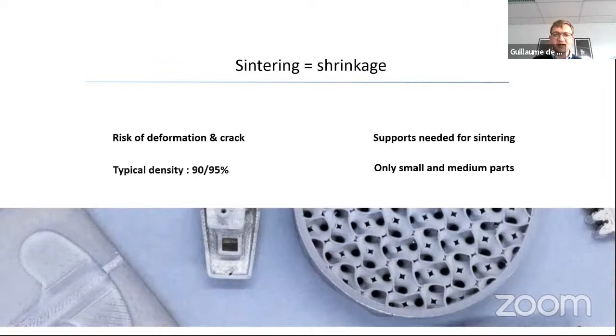The one thing which goes with that is if you have some densification without melting, the material needs to come from somewhere, and what happens is the part will shrink. And that's really one of the major problems with MIM-like technologies. If you sinter a part, you have shrinkage, and shrinkage is going to pose a few problems. The first one is obviously you'll have some risk of deformation and cracks. Secondly, you will get to dense metals, but not fully dense. It's very difficult by a sintering method to get to more than 95% density.